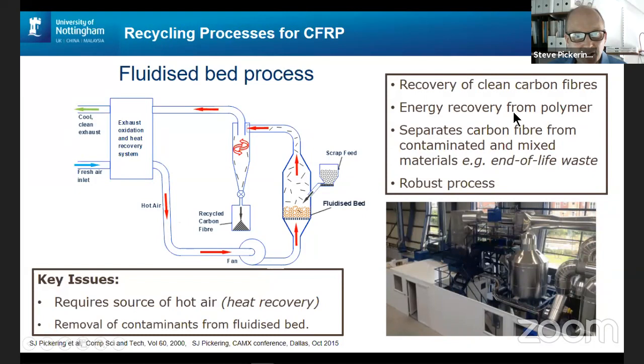You get energy recovery from the polymer, and as well as being a fiber recovery process, it's effectively an air classification process. So it's able to separate out different contamination from the material as well. So if there's any metallic parts in with the waste, then that stays behind in the fluidized bed. So it's very good, and also if there's any other contamination that is oxidized in the process. So it's very good for end-of-life waste, and it's a robust process.